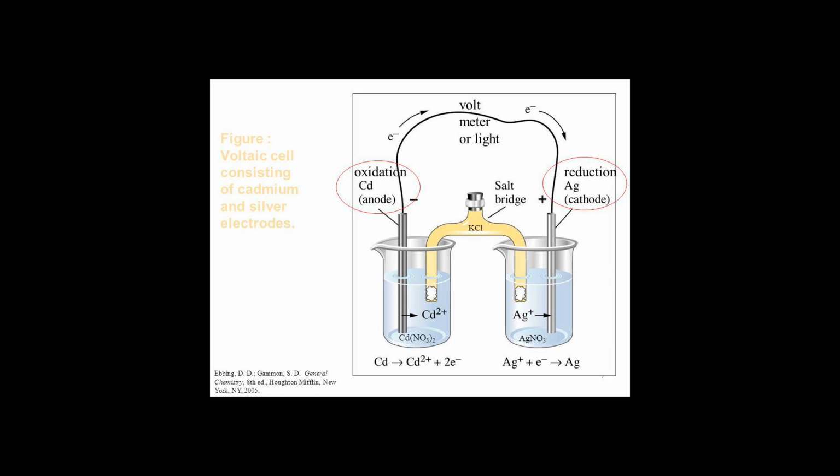Theoretically, as little as 2 grams of silver are required for each ampere-hour of capacity. But practical cells require between 3 and 3.5 grams because the charging voltage is higher than the discharge voltage. The watt-hour efficiency of a silver-cadmium cell is about 70%. Ampere-hour efficiency is about 98%.